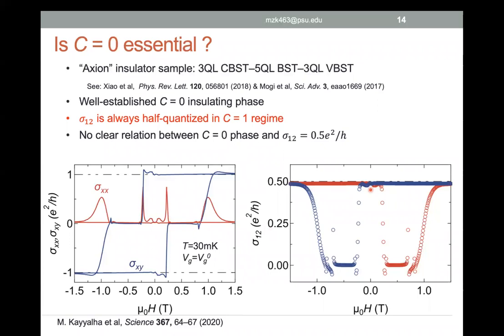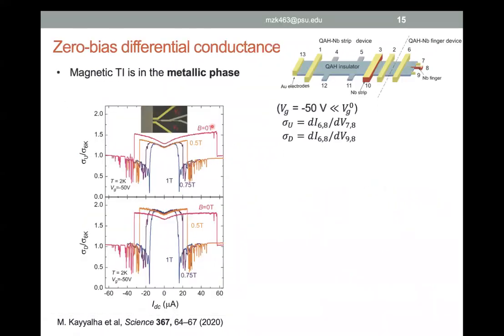conductance value. So then I wanted to actually look into the interface between the niobium and the quantum anomalous Hall insulator. So I use this niobium finger again. The reason I'm using this finger is because the superconductivity is weaker there, so I can actually study some Andreev reflection processes here. So here I'm looking at the two terminal conductance between the niobium finger and the magnetic TI.